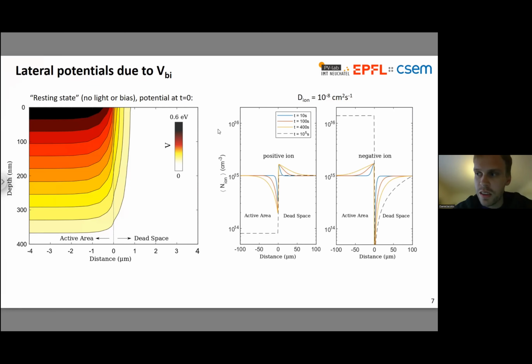So you can see that these time scales, I've chosen a fast ion just for this demonstration. So that's a relatively high diffusion constant for the ion, sort of within the range of reported values for halide defects in particular. And you can see that migration is happening over tens of microns here in the simulation already at a few minutes. And then over hours, you can have relatively large redistributions of ions from one side of the boundary to the other. So factors of 10 in ion density as a result of this lateral migration once the system comes to equilibrium.